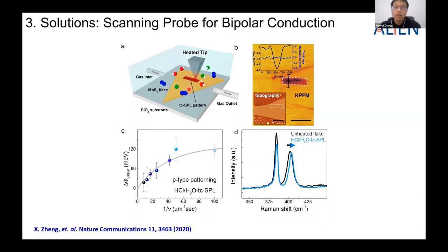For now, instead of using the PPA polymer, we use the scanning probe, the heated probe, to interact with the 2D layer directly. Okay, as you can see here, by introducing certain gases, by controlling the gas environment, after patterning, we could see in topography, we did not introduce any changes, which means we maintain the topography of the material. However, if we test with Kelvin probe force microscopy, the KPFM, which is consistent with the Fermi level, we can clearly see a dip in the patterned region. It means the heated tip actually introduces doping into the 2D layer and tunes the position of the Fermi level. And in this case, we introduce p-type doping in the 2D layer.